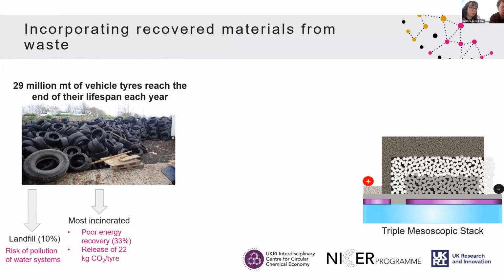Another option would be to burn them to get energy, but we are releasing like 22 kilograms of CO2 per tire, so that's not ideal, and we're not even getting that much energy because it has a poor energy recovery, like 33%. Another pathway is the standard recycling. They just get chopped and made into sport pitches, but at the end of the day, if they just get chopped and deposited again on the land, they're still subject to potential contamination or pollution of water streams because it will rain on them and that will percolate.